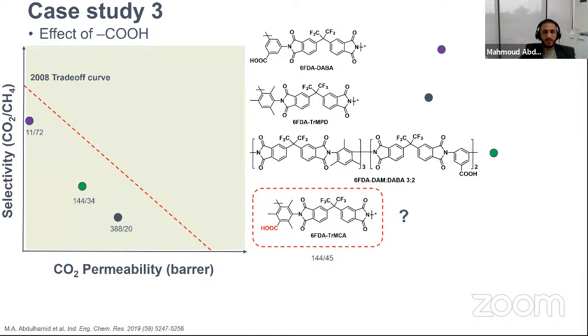So the performance of this material was at this position here, where it has a permeability of 144 barrer and selectivity of 45. And this is a very good combination for industrial approaches, as reported by one of the pioneers of gas separation, Dr. Baker, that if you have a material with a permeability around 120 to 140 with selectivity of 40, this would be very promising for different types of separations.